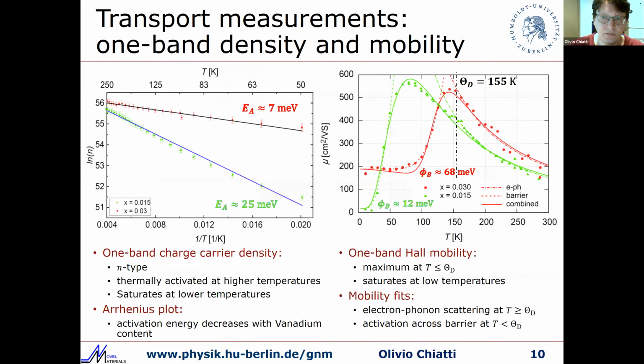We can do some further analysis of these results. In particular, we can do an Arrhenius plot for the charge carrier density. We already see that it's an n-type conduction, so these are electrons. And at higher temperatures, the charge carrier density is thermally activated, and at lower temperatures, which are not depicted here, it saturates. From the Arrhenius plot, we determined from linear fits some activation energy, and we can see that at lower vanadium concentration, the activation energy is larger than at higher vanadium concentration, which is consistent with the ARPES picture, which shows that the chemical potential moves closer to the conduction band.